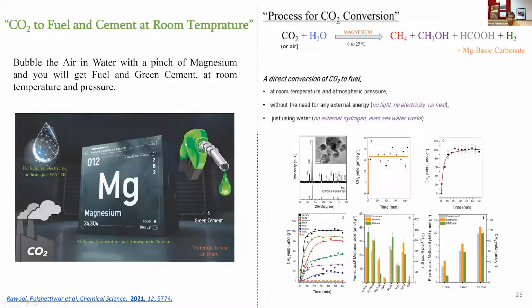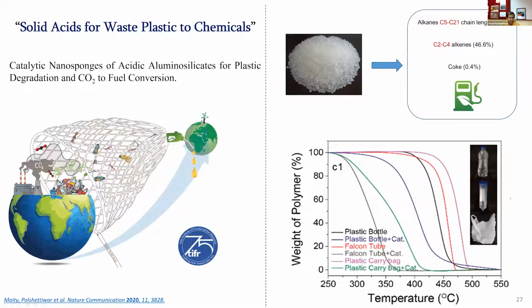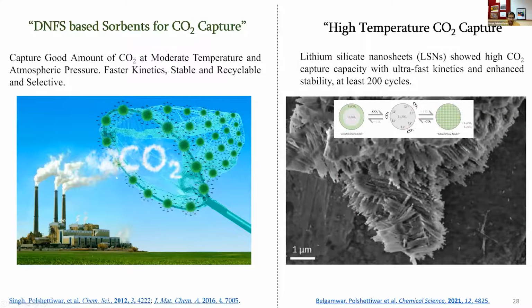This is another example where we prepare a solid acid, with acidity close to the zeolite, but it is a mesoporous material. So that allows us to even degrade bigger molecules, macromolecules like plastic polymers. And we also use the same material for CO2 to DME directly. We also worked on CO2 capture, low temperature CO2 capture as well as high temperature CO2 capture, which could be the first step to take on climate change.